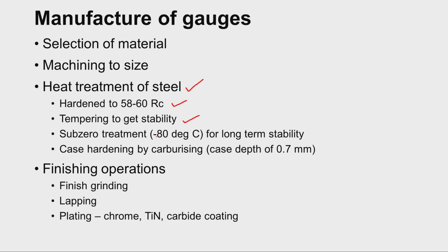And sometimes sub-zero treatment, that is the gauge blanks are placed at minus 80 degrees Celsius for long term stability. And then case hardening by carburizing also is sometimes performed on the gauges to improve the hardness of the gauging surfaces. So in that case, case depth of 0.7 millimeter may be required. So after this heat treatment, the gauging surfaces are ground, and then they are lapped, and all sort of finishing operations are performed. And then if plating is required, plating is also performed, and then again after the plating is over, again they are ground and lapped to get the proper size.